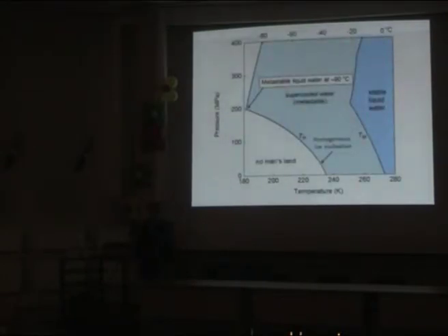Water could be supercooled, actually amazingly deeply supercooled. For example, this is a melting line, the equilibrium thermodynamic melting line between water and ice. Ice could be in different forms, but this is not the point today. Most importantly, for example, at 200 megapascal, which is 2,000 atmospheres, water could be liquid in a huge range, 90 degrees. Even at ambient conditions, we could supercool water until the homogeneous ice nucleation, and unfortunately in bulk water, experimentalists cannot penetrate through this line because spontaneously supercooled, metastable water crystallizes. But still, it's a very, very low temperature. Next slide, please.